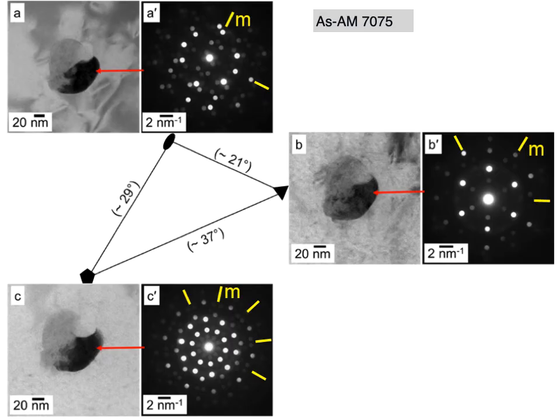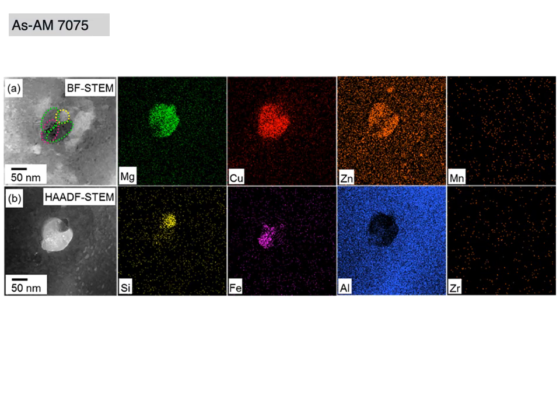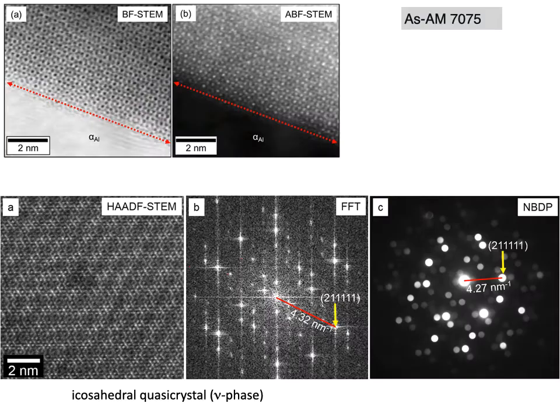What we actually have, however, in the additively manufactured alloy of 7075, in 3D printed 7075, we can see that in all three zone axes from nanobeam diffraction of the same hardening particle, we exhibit twofold, threefold, and fivefold symmetries of an icosahedral quasicrystal. The quasicrystal has a unique magnesium copper zinc composition and has never previously been seen before in terms of either composition or indeed in crystal structure. So shown here close up, we can see the crystal structure, which we've termed new phase, not because it's new as in not seen before, it is that, but it's been named after the Greek letter nu.